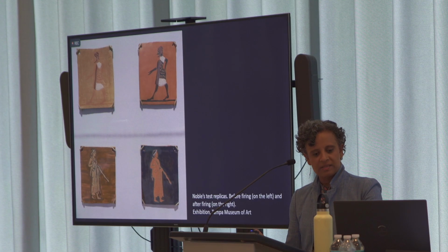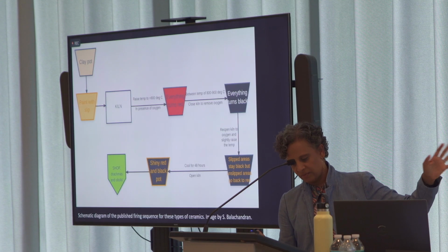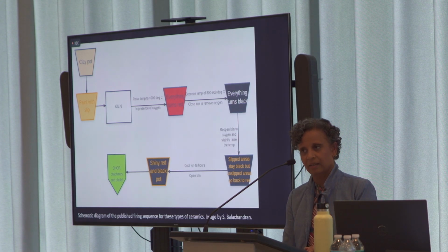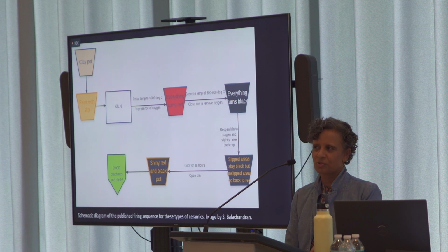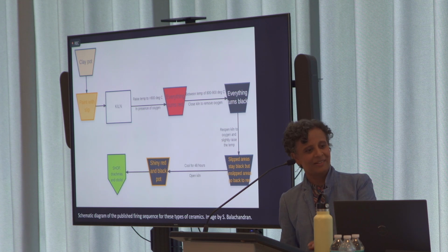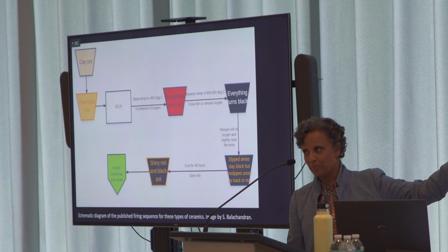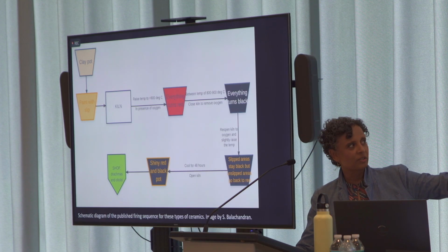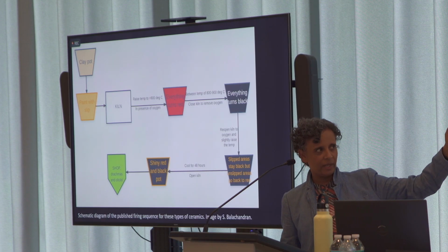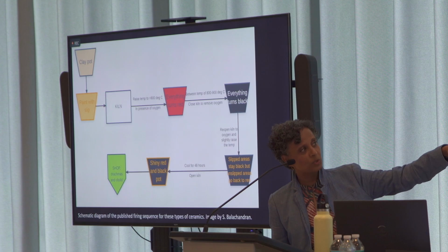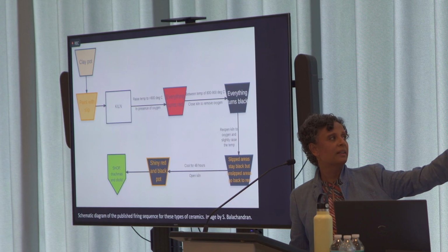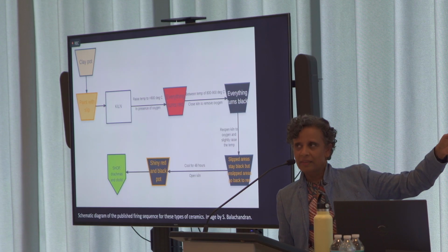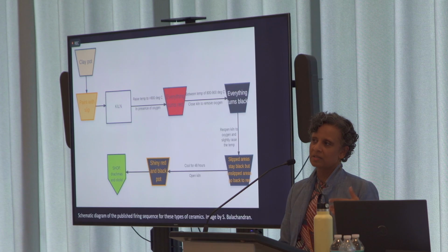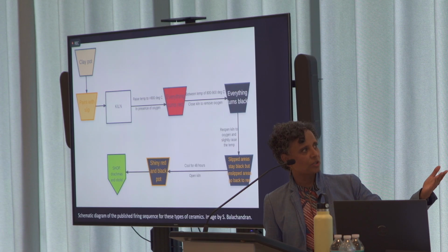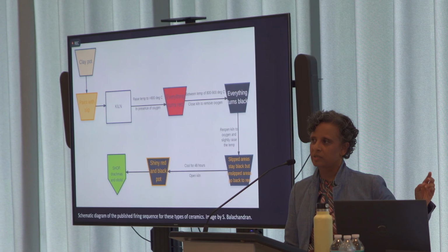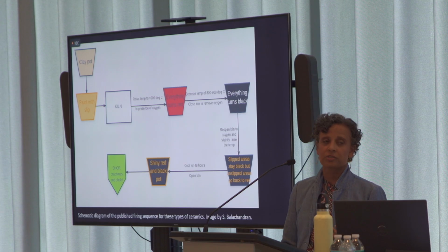So this is the process that he identified in his book, and I've just made a little easy graphic. And you're all here to hear about Athenian ceramics, so we are about to get in the weeds, all right? So you've made your clay pot, you've made that structure, you've painted it with slip in whatever way, and now you know there's a drawing step in between, and then you're going to put it inside a kiln. The way that usually it's described is first the temperature is raised from room temperature all the way to over 900 degrees centigrade in the presence of oxygen.